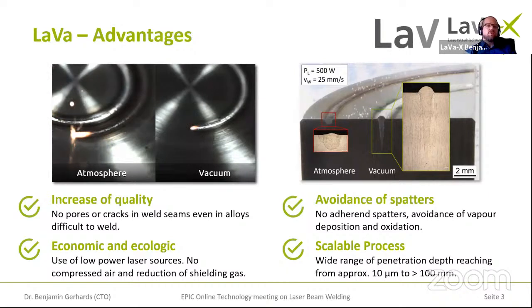And last but not least, we have a very scalable process. We can reach penetration depths from approximately 10 microns up to more than 100 millimeters. So we are in no way inferior to electron beam welding at this stage. So all the benefits from laser beam welding and the benefits from electron beam welding, with nearly no drawbacks, except for maybe the size of the vacuum chamber.